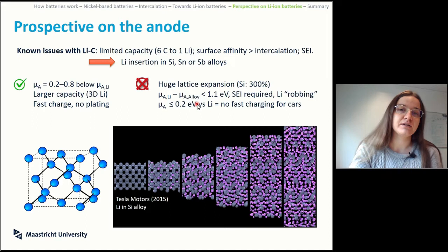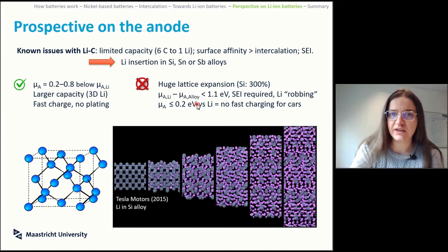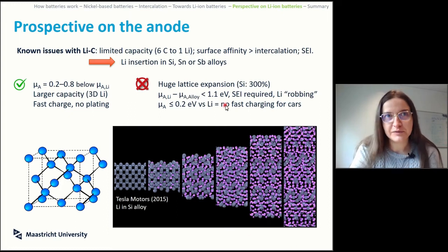The difference of lithium and the alloy in terms of potential energy means that, first of all, you still have the solid electrolyte interface, and you rob the lithium away from the alloy, even though it goes in at crazy degrees, and you can actually intercalate a lot of lithium in. You still have this issue of you rob it away from the surface, and apart from the expansion problem, given this issue of putting the lithium inside, you cannot do the fast charging of your battery.